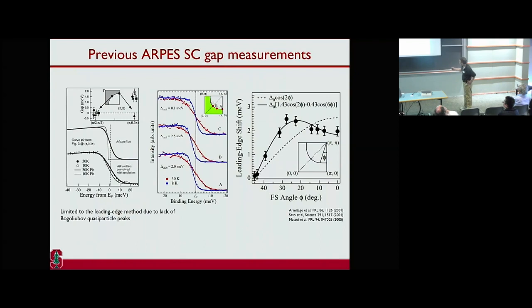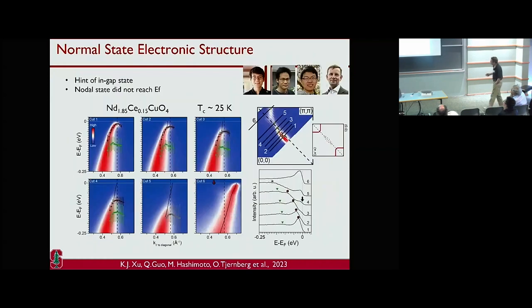Again, that's the data from Peter's thesis 2 decades ago. Back then, we would not be able to see this temperature dependence, to show this to be a superconducting gap. We were just using the leading edge, and that's Matsui et al. showing similar work, and they began to show that, hey, this thing was non-monotonic. You see, okay, that's 2005, okay? Back then they said, okay, this is just a higher harmonic of a D-wave gap. Okay, that's where it is. But the key question was that because we also have a pseudogap in a similar momentum space, is this just the residual, because it's a small effect, residual of this pseudogap? Okay, so that's where things stand, and that's the more recent data looking into that.